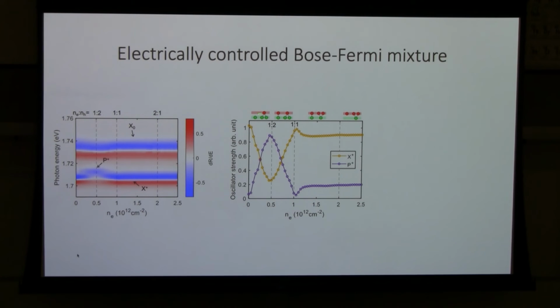What we can see is that initially, when we have 0 electrons, all the holes are free, so you have a very large interlayer exciton signal, but no P plus signal. That means you have no trion. When you add electrons, the electron will grab 2 holes and form a trion, and it will reach a maximum when the electron to hole density ratio is 1 to 2. When you keep increasing the electron density, the electron will take additional holes from the trion and form an exciton-trion mixture, so the trion density will start to decrease. If you keep increasing the electron density, in principle you will form excitons and electron-trion mixtures, which cannot be read out when we only probe holes in the system.